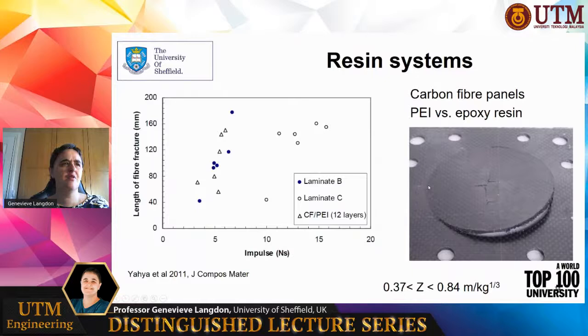And on the right-hand side of this screen, you can see an image of one of Yasir's experiments, where we tested it with a circular exposed area and clamped it around the edges. So the holes you see are for the clamping frame. What we see here is a very beautiful example of shear around that boundary edge where the panel is coming completely out. But you also have cracking in the middle, which makes this an extremely interesting failure mode, because it is in between the localized and uniform area. So you would have had a displacement of the panel overall, cracking in the center, and then shearing around the boundary, causing almost that entire disc to come out as one piece.